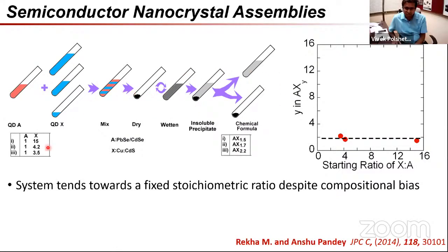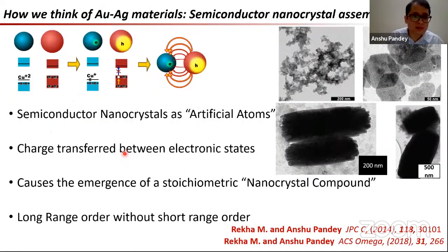So what we have are two specific nanocrystals in this example, lead selenide and cadmium sulfide. So this has basically got a lower conduction band, sorry, a higher valence band offset, while we have a copper doped nanocrystal on the other side. So copper has a state available in which it can accept electrons from the valence band of lead selenide. So following that, you get charges appearing on both the nanocrystals, sort of as is shown in this schematic. The ligands on these nanocrystals are still kept on.